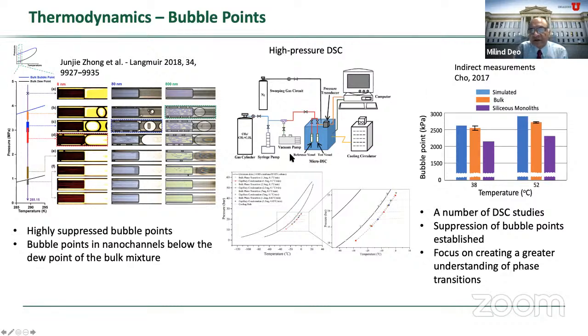We have used DSC in our own work and did some experiments with silica. Our paper was published back in 2017, but these were indirect measurements. These were not direct measurements like this. So these had more factors than just the nano porosity that this group looked at. But anyway, the evidence was pointing out that you have suppressed bubble points. You can see there is a group in Wyoming that also found that the bubble point is suppressed.